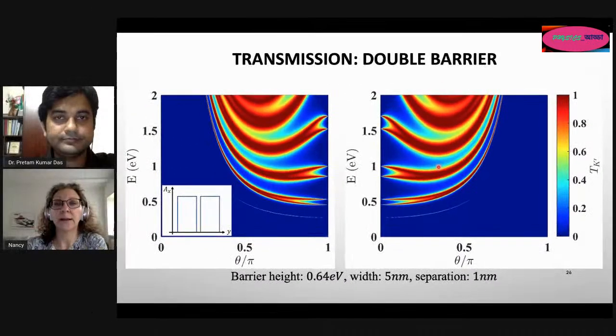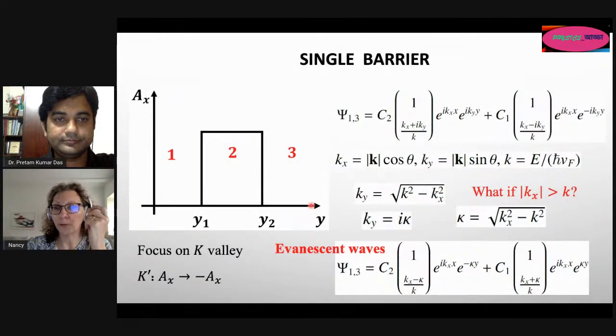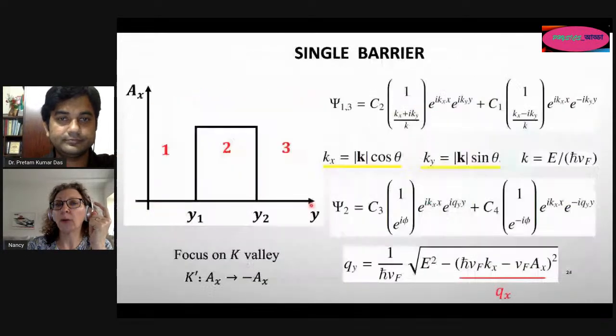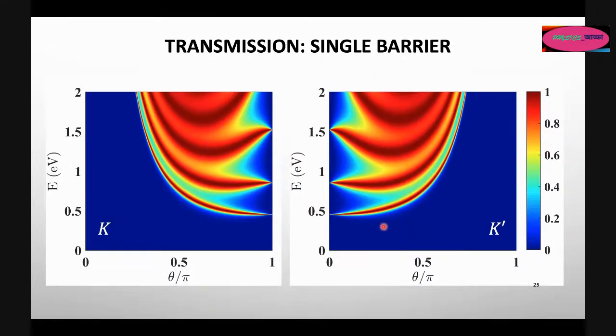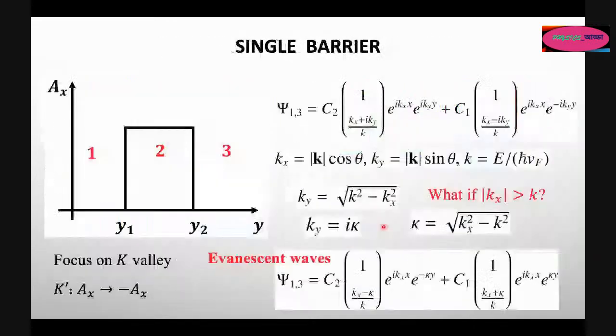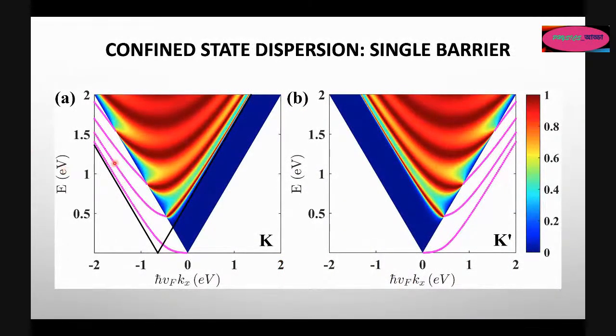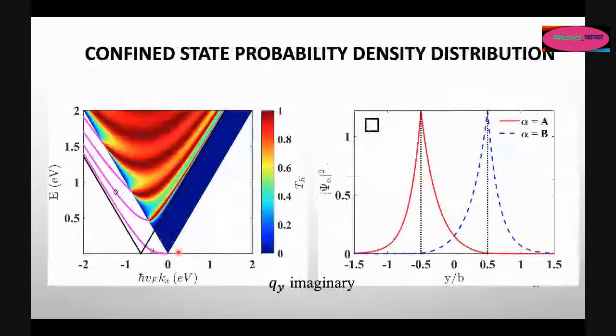So given the time, I am showing here results for the double barrier, and very similar to the other, the resonance is split. But what I want to point out is that these states are all plane waves, all imaginary exponents. So we ask: can this structure also behave like the quantum dots, creating localized states? To create localized states, what we need is a momentum that is imaginary in this region. So we look for evanescent waves that die inside the barrier, and effectively we find states that have energy versus momenta that come with a discrete spectrum, and these are localized in the barrier.